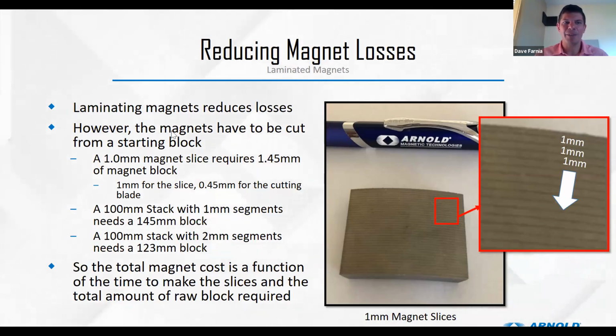Drawback is that these magnets have to be cut from a starting block. So if we have that 1 millimeter magnet segment, we have to use a basically 1.45 millimeter block in order to get that. 1 millimeter for the actual slice and then 0.45 millimeters for the cutting blade, which means that for a 100 millimeter stack with 1 millimeter segments, we need a 145 millimeter starting block. A 100 millimeter stack with 2 millimeter segments would only need a 123 millimeter block.